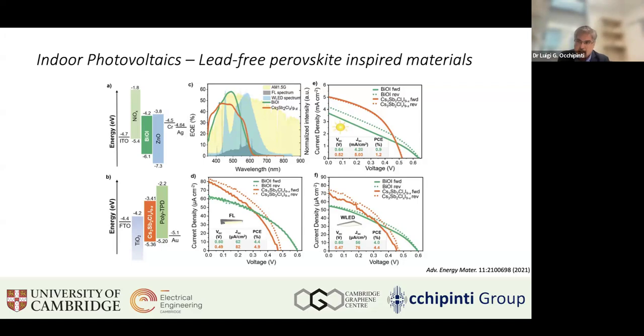Finally, another interesting finding was that although these materials have a very low efficiency both indoor and outdoor, while outdoor the conversion efficiency is in the range of 1%, it increases by 4 or 5 times when it goes from outdoor to indoor. Yes, and they're also stable for a long period of time, which is promising.